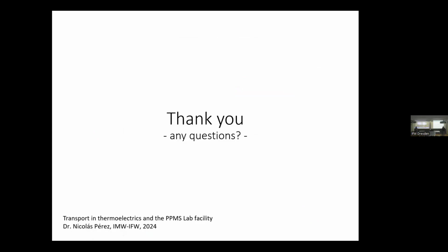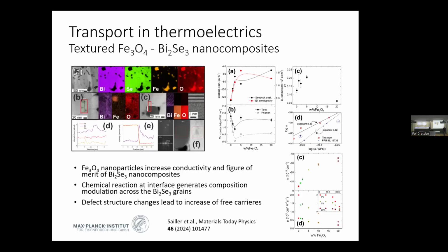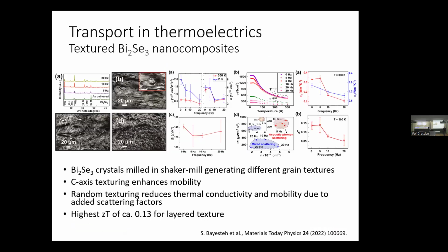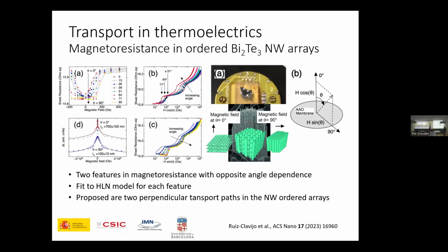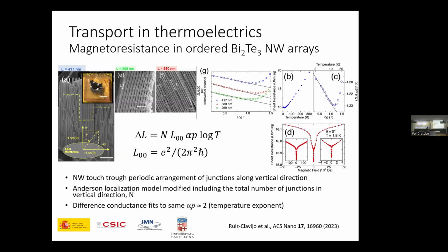From my side, the first question: these are bismuth selenide, bismuth telluride type systems, which are studied as topological insulators, right? Yes. What is the difference? Why do they grow in nanorods and not in flakes? That wasn't done on purpose. That was because they were grown inside a template. A template was created on aluminum oxide, which contains the holes where this grows, filling the holes. And the axis is along the rod. Yes.